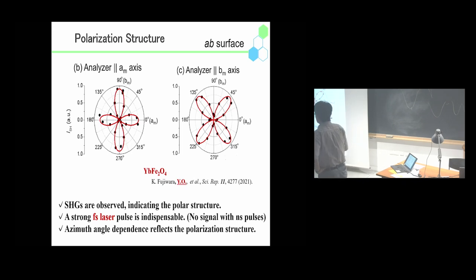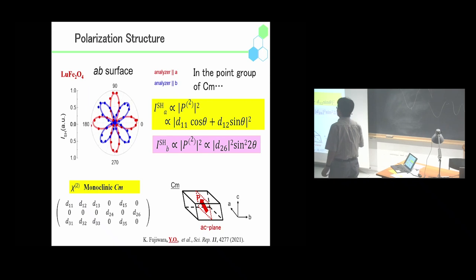Okay, so the next problem is how do we understand this angle dependence? This is the azimuth angle dependence of the SHG in lutetium Fe2O4. The angle profile is almost the same as ytterbium Fe2O4. To understand this angle dependence, we assume the monoclinic Cm, which is one of the candidates based on the neutron diffraction measurements. According to the International Tables, we can easily see the contracted chi2 tensor like this for this symmetry.